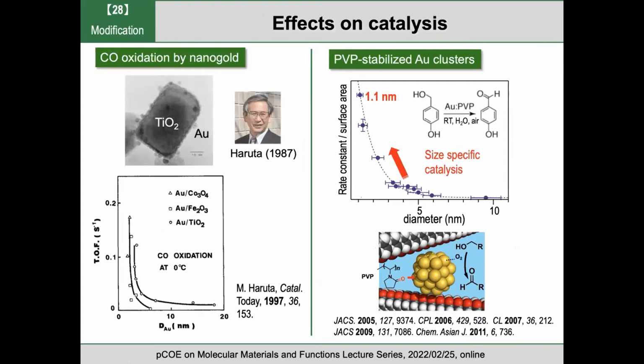Okay, so the ligand or surfactant is important when we think about catalytic applications. And this work has been inspired by the discovery by Professor Haruta a long time ago. He discovered that gold at the nanoscale can oxidize CO, and gold clusters can act as a catalyst for CO oxidation. Very sadly, he passed away very recently. But anyway, we found this discovery very interesting, and we use polymers as a stabilizer of gold clusters.